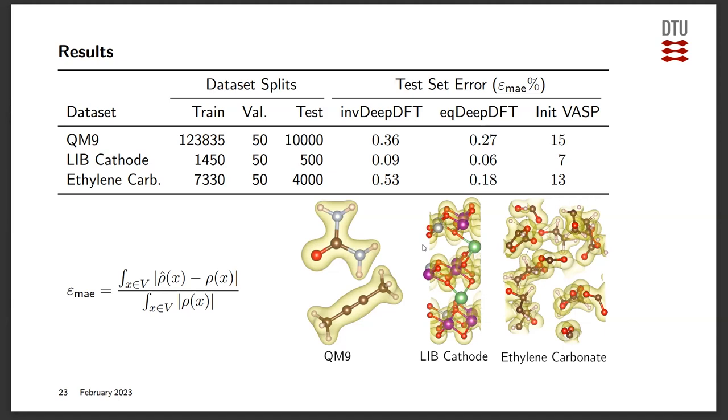Okay, so for the first one, you include many molecules with different distances, so it's very comprehensive. The second and the third one are specific crystals with specific coordinates? So this is some crystals where you take out atoms, make some vacancies and then optimize the structures. We have 2,000 different structures. We have some prototype structure and we take out some and make some vacancies. And this one is a molecular dynamics simulation at very, very high temperature. The species are C, N, O, F and hydrogen.